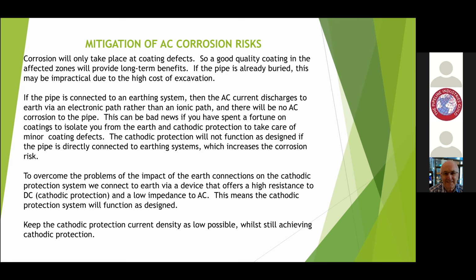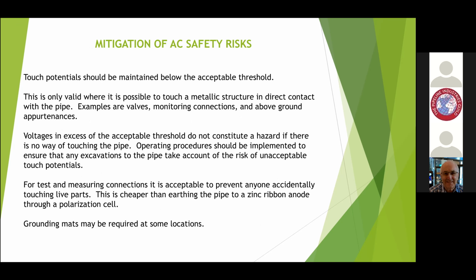So what we have to do is connect the earth of the pipe through a widget that stops the cathodic protection leaving the pipe, but lets the alternating current leave the pipe. And those devices are normally called polarization cells or polarization devices. So you can do that, but of course you have to know where to put those devices and where to put the earthing. And that normally we do by modeling, which we'll talk about a bit later. And we also, to fulfill one of the requirements of the AC protection criteria, need to keep this current density as low as possible, which is not always the case. Many pipes have too much cathodic protection current.